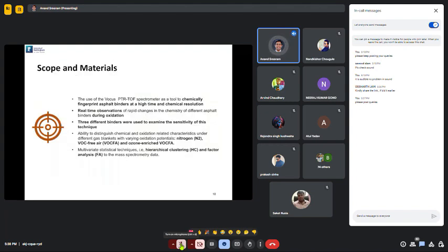So in terms of the scope of this study, we looked at the use of the Vocus spectrometer as a tool to chemically fingerprint asphalt binders at very high time and chemical resolutions. We looked at things like the real-time observation of rapid changes in the chemistry of different asphalt binders during oxidation. We used 3 different asphalt binders or bitumens to examine the sensitivity of this technique. And we also used different kinds of air blankets that have different oxidation potential.